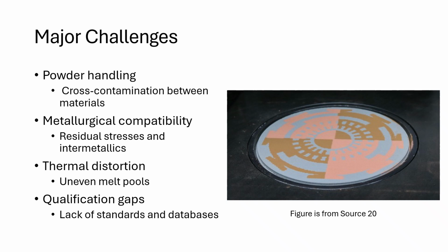While progress is rapid, several barriers remain. Powder cross-contamination can cause unintended gradients. Dissimilar metals solidify in different manners, forming brittle intermetallics or high residual stresses. Thermal management during the print must also account for reflectivity and conductivity variations between the different gradations. Finally, there's little standardization for what the qualification framework should look like for these materials, which hinders industry adoption and makes designers more hesitant to use this technology for new products.